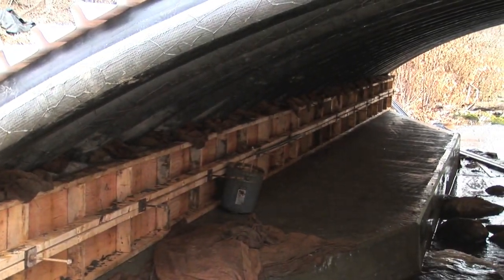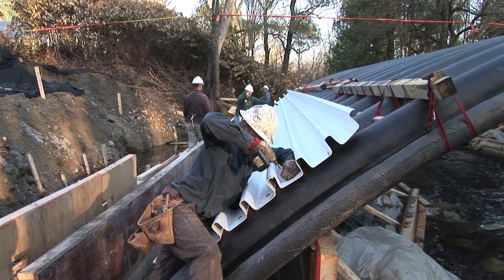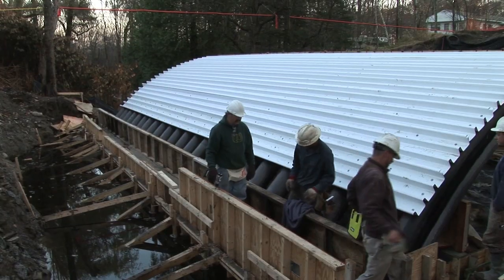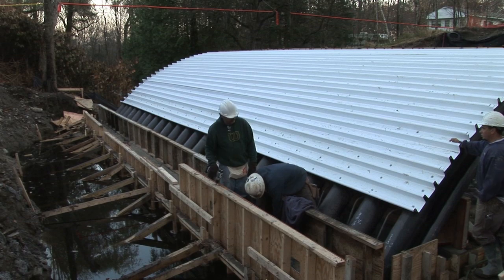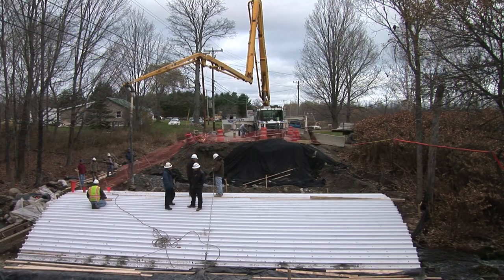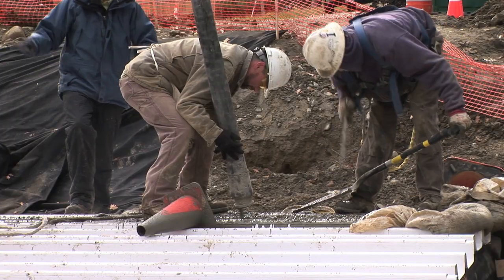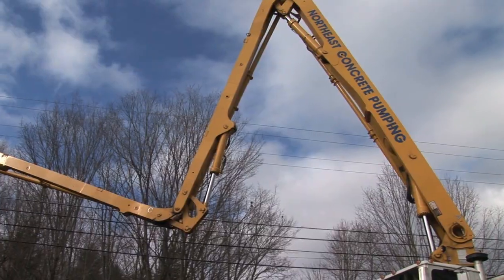Once precisely in place, the base of the arches were encased in a shallow concrete footing. Composite corrugated decking was placed over the empty arches using self-drilling screws. The self-drilling screws become concrete anchors once the arches are filled with concrete. The arches were filled with a self-consolidating, expansive concrete mix through individual holes located in the top of each arch. The aggregate time it took to fill all 23 arches with concrete was only about one hour.